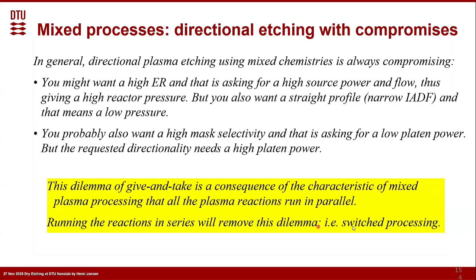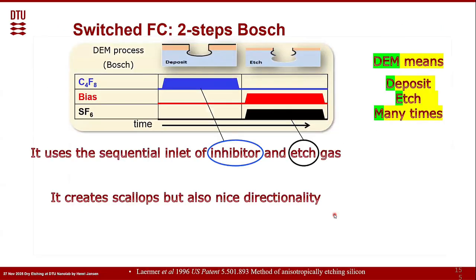Now we can remove that dilemma by putting it into a cycle, the switch process. I will start with the typical one everyone in the audience probably knows, the two-step Bosch process. It uses a sequential inlet of inhibitor, which is passivating the process, let's say with C4F8. And then after that, for a little moment, you use an SF6 gas. At that moment you supply the DC bias, and of course in the beginning it still has to remove the fluorocarbon we just deposited here at the bottom, but when it's gone, it will continue with etching.